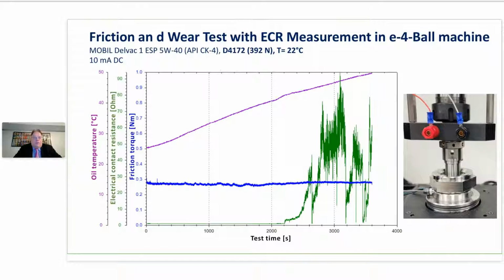So in a classic 4-ball test, 400 Newton, 1 hour of test, you see here the evolution of the coefficient of friction, the evolution of the temperature or the friction torque, and you see here the contact resistance. For a long time during the test, nothing happens, and suddenly the contact resistance increases because a specific tribofilm is formed. And this is now really the debate if such a tribofilm formation is good or bad. At least for load carrying capacity and wear protection, it's certainly good. But in terms of electrical properties, the question is, when we have a build-up of electrical resistance on the surface, does it generate arcing and other effects which will degrade the lubricant?